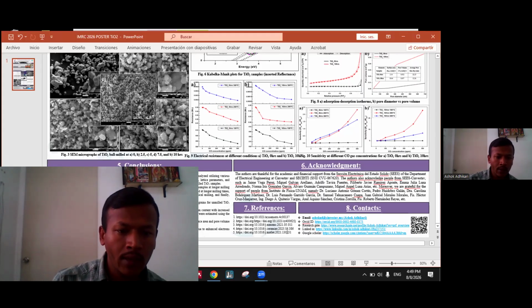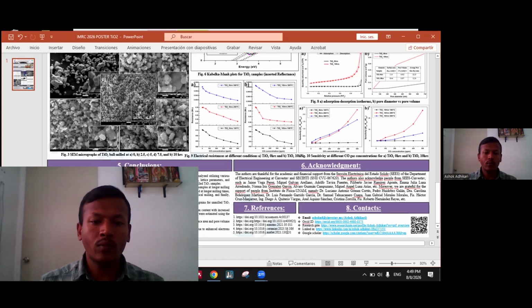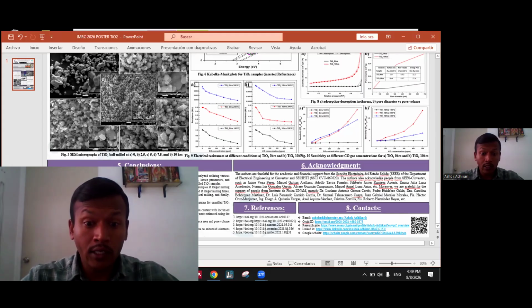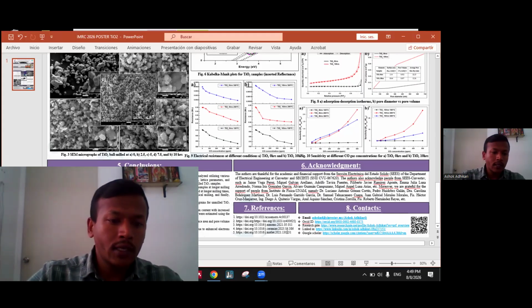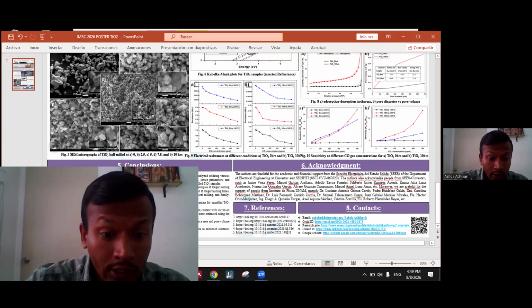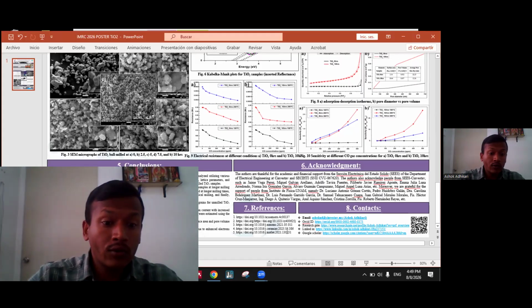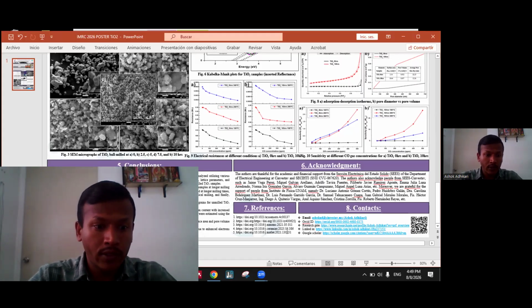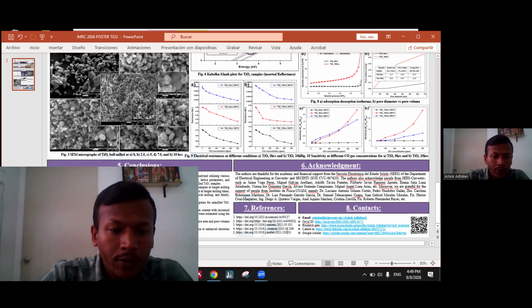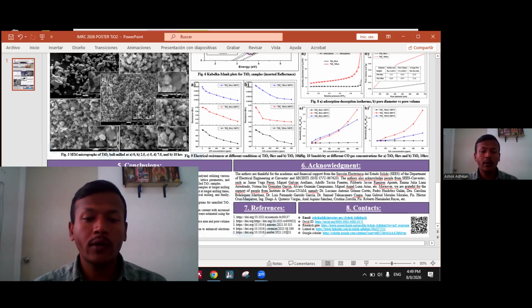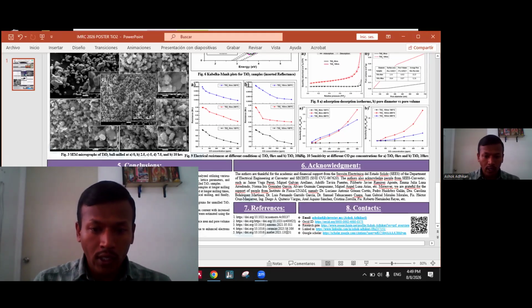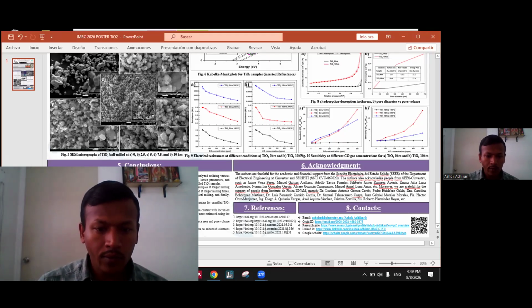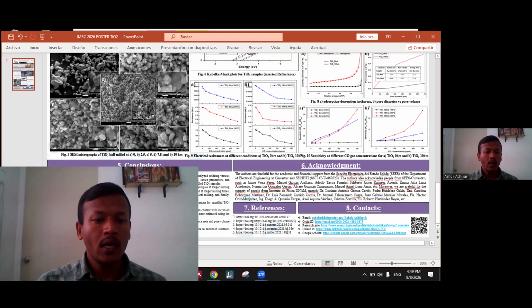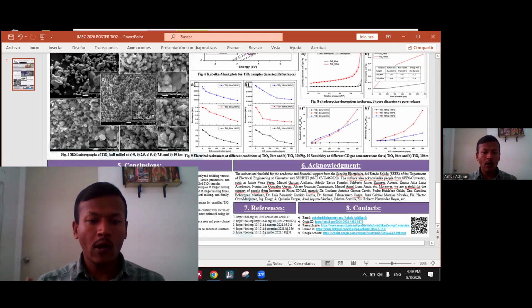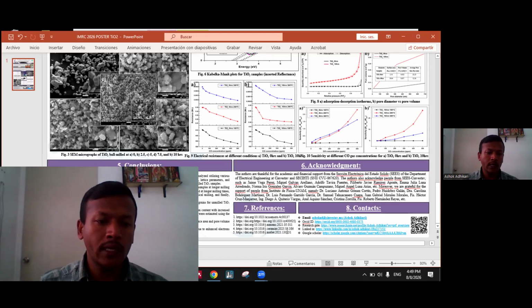From morphological analysis, the micrographs show larger grains, more than 1 micrometer, with geometric shapes for the unmilled sample, and similarly irregular shaped homogeneous nano-sized particles for the milled samples. EDS measurement identifies the uniform distribution of oxygen and titanium atoms, as well as the decrease of oxygen content with increasing milling times. And the band gap of the samples, estimated using Kubelka-Munk, was found between 2.83 and 3.2 electron volts with increasing milling times.